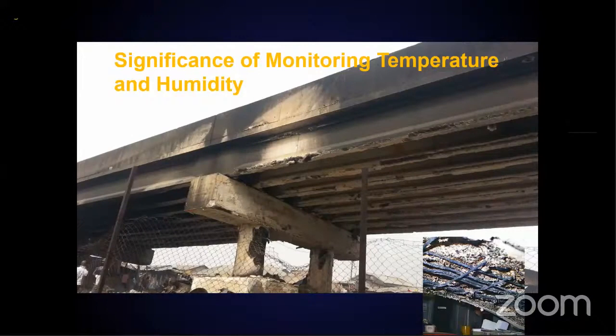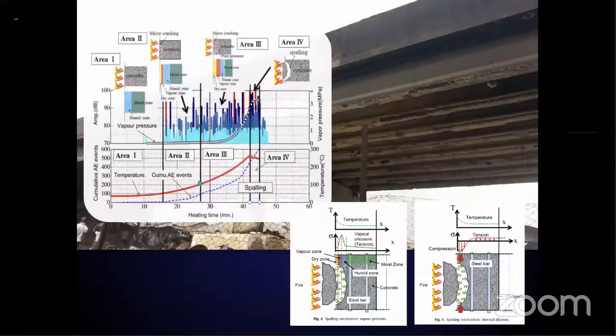This is because whenever you have a temperature between 150 to 250 and above, that is 400 degrees, the calcium hydroxide of the cement hydrates and creates water steam. That's the basic thing. This steam tries to increase the pressure, and thereby it pushes the weakest section. Therefore, you lose the concrete on its surfaces.